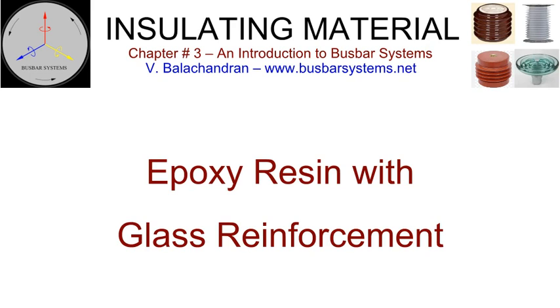High-strength, long, profiled insulating components are manufactured by a process called pultrusion. The process comprises a large number of glass filaments passing through a mix of epoxy resin and hardener and converging to a profiled mold and pulled at the other end. Glass-reinforced epoxy resin components are used in busbar systems as support blocks, bushings, phase barriers, and tie rods.